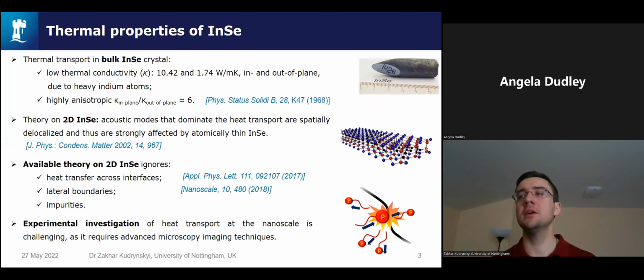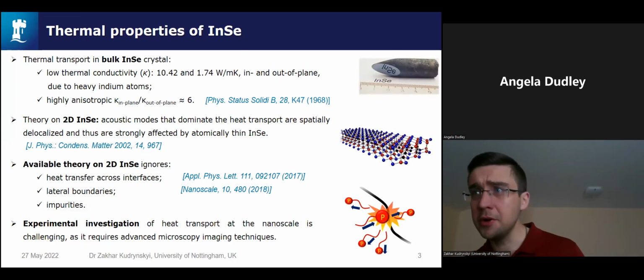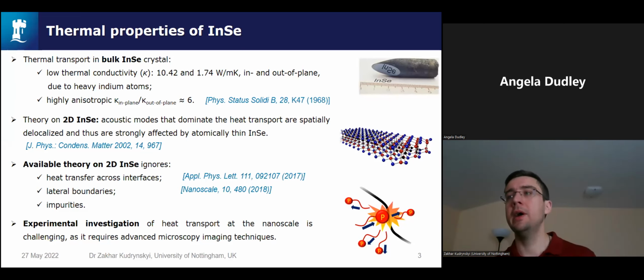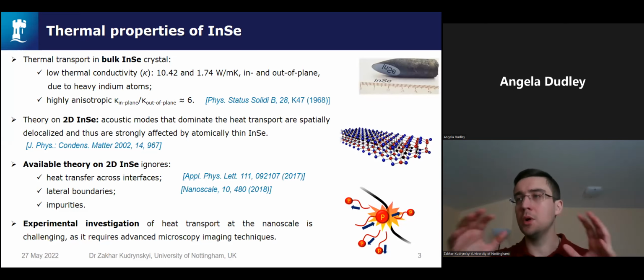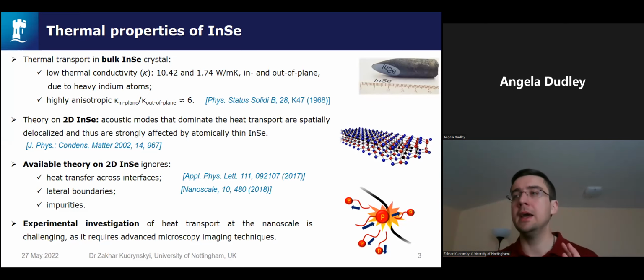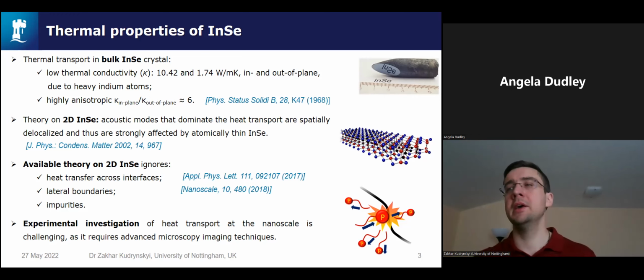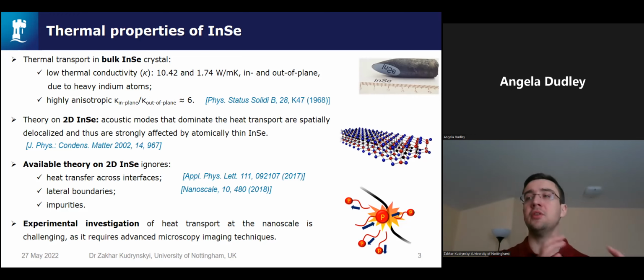This low thermal conductivity originates from the heavy indium atoms, but little is known about thermal transport in the 2D layers. Theoretical atomic displacement studies showed that whereas optical modes are mostly confined within indium selenide layers, acoustic modes that dominate the heat transport are spatially delocalized within different van der Waals layers, so they are more strongly affected by atomically thin layers. The problem with the currently available theory is that it ignores a few important things, such as heat transfer across the interfaces, lateral boundaries, and phonon scattering by impurities.